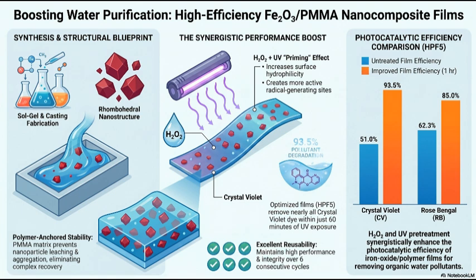However, despite this flawless engineering, hematite carries a fatal flaw in its physics. Right, and that flaw is something called a short-hole diffusion length. The paper mentions it's only about 2 to 4 nanometers. Yeah, and what that means in practice is that after the UV light catapults the electron across the band gap, the electron almost immediately falls back down into the hole it left behind. Oh man, so it just gives up. Pretty much. The excited charge carriers recombine in a fraction of a second.